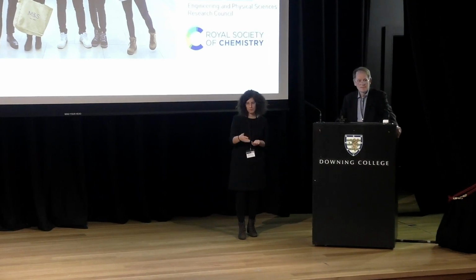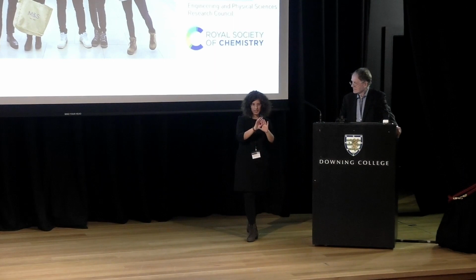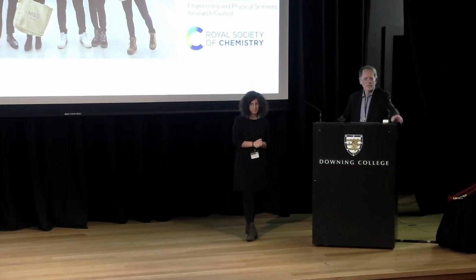But what you can do is work with functional polymers. So instead of the boring, just alkyl polycaprolactone structure that I showed, you can have pendant groups in there that you can covalently attach drugs to, through, for example, linkers that then can degrade in vivo, such as ester linkers or amides or so on. And then you can create a nanoparticle that way, and you can create different morphologies, and you have great control over it. And then you can degrade that selectively and release basically the drug that is attached. So yeah, you can do it, but not through encapsulation, but through covalently attaching it to part of the polymer.